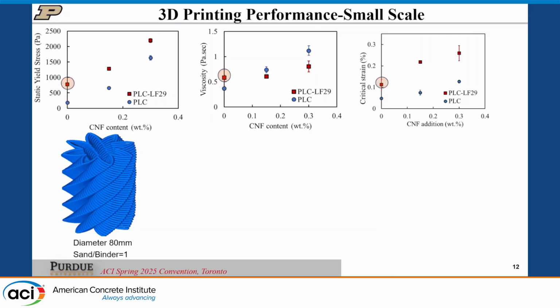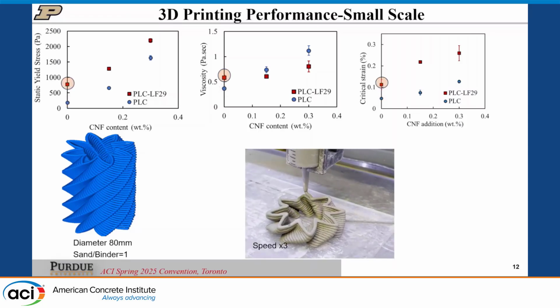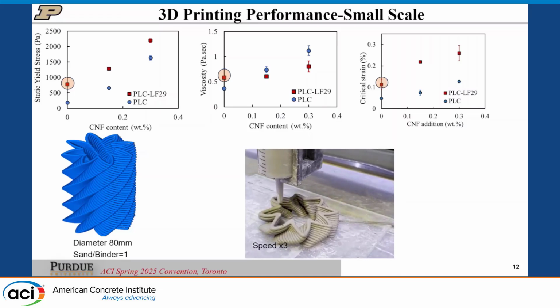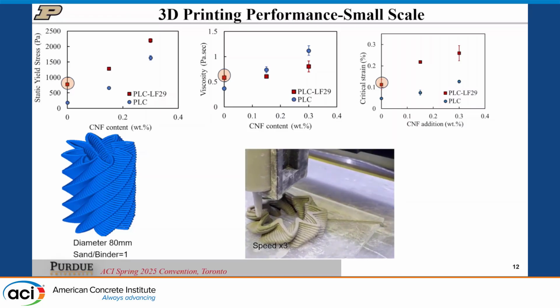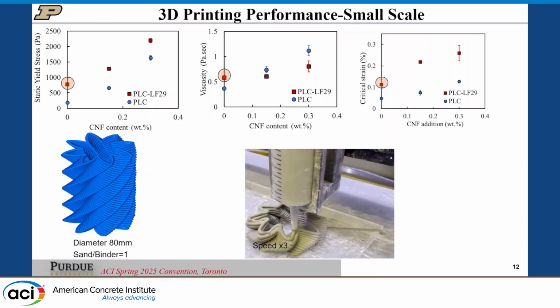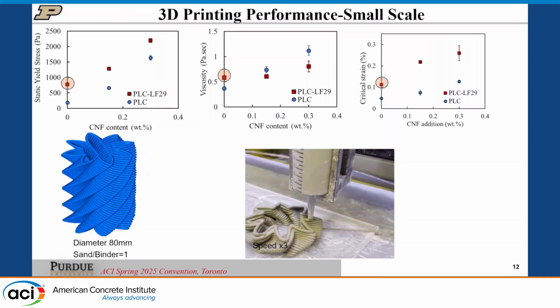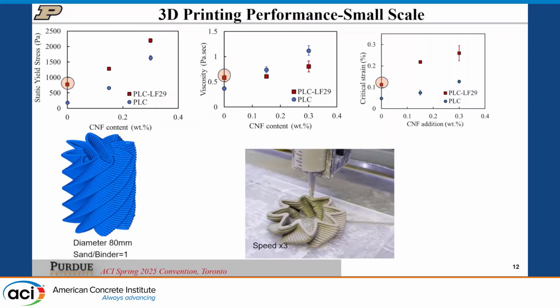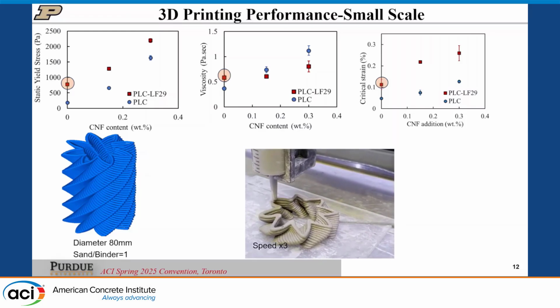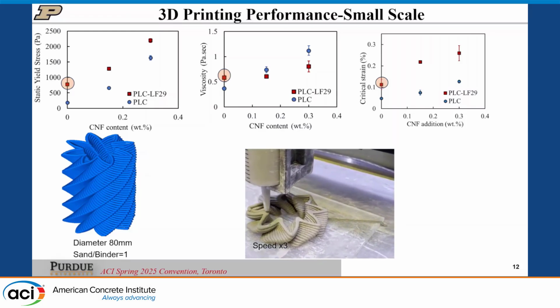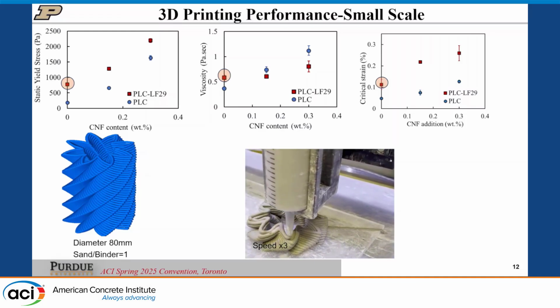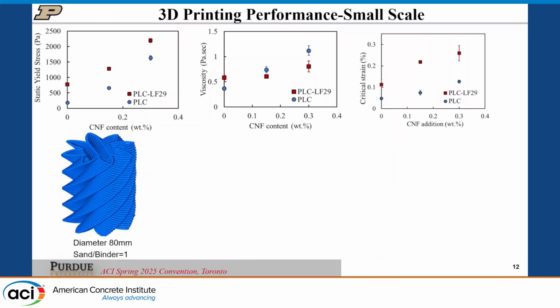When we look at only adding limestone fillers, relying only on increased packing density, we see the print starts buckling. This is where you see that top wall starts to buckle inwards, mainly due to having low elastic modulus of our print.